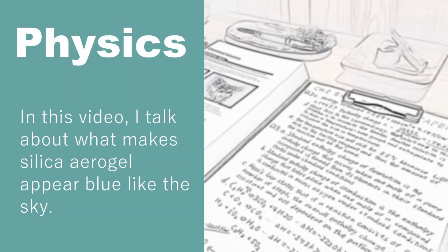So instead of evaporating the water, we put lots of pressure on the jelly while raising its temperature so that the water will be supercritical. At this point, there will be no difference between a gas and a liquid. By going through this supercritical phase, the water can apparently leave the jelly gently as gas without undergoing destructive evaporation.